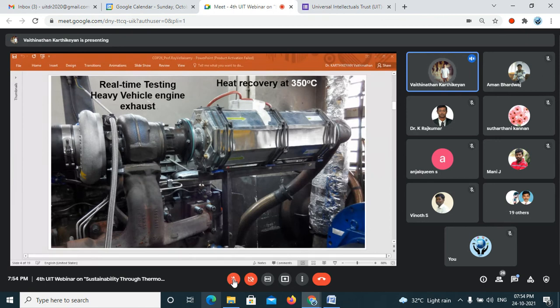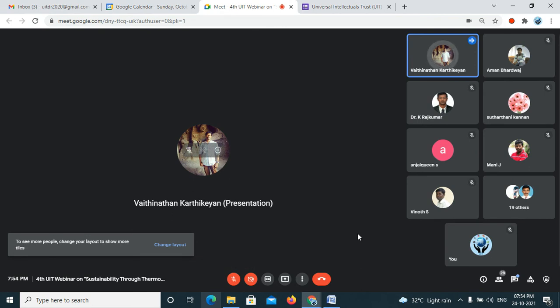And then this is the device which we fabricated, which uses the zinc antimony structure. And this is the heat harvesting block. Over the heat harvesting block, we placed our thermoelectric generators and packed them perfectly. Then we gave it for testing at 350 degrees centigrade, and we got a good efficiency. I mean, we used the hot air output for the power conversion. As zinc antimony is non-toxic, we are able to develop a non-toxic thermoelectric material operating at high temperature, and it is lightweight, and you can control the power output. As you can see in this structure, we pass the hot